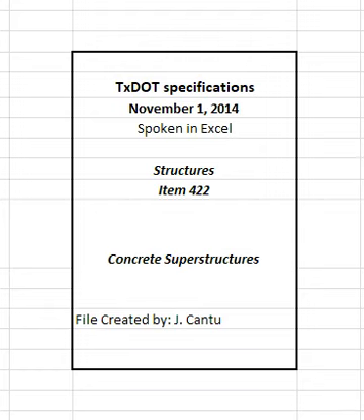Fill screed rail support holes with concrete, and finish them to match the top of the slab. Provide a uniform microtexture using a carpet drag, burlap drag, or broom finish. Finish the surface to a smooth sandy texture without blemishes, marks, or scratches deeper than 1/16 inches.